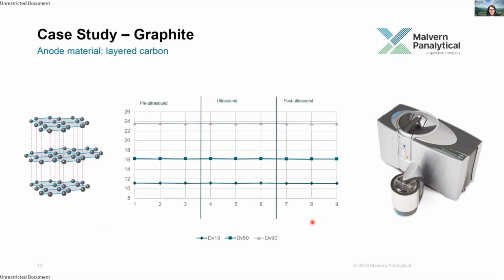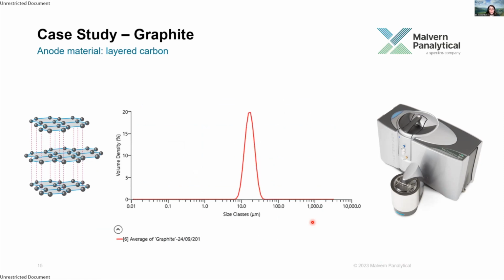And then finally, here we're looking at an anode material, so graphite, which again has been successfully dispersed in water with a surfactant. So again, the dispersion is very stable. We don't need ultrasound to disperse this material. And this sample has a very narrow monomodal distribution, which is obviously going to impact the slurry viscosity for the reasons we discussed earlier.